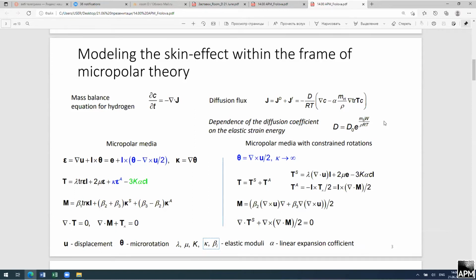Here we try to explain and to model the appearance of such a boundary layer with a stress strain state that differs significantly from the bulk material. So we start from the mass balance equation for hydrogen and consider stress-induced diffusion. We assume the diffusion flux consists of two terms. The first one is due to the gradient of concentration, and the second one is due to an additional driving force. Here, as usual in hydrogenation problems, we consider pressure as the additional driving force. And additionally, we assume dependence of the diffusion coefficient on the elastic strain energy to account for the influence of the stress strain state on the diffusion process.